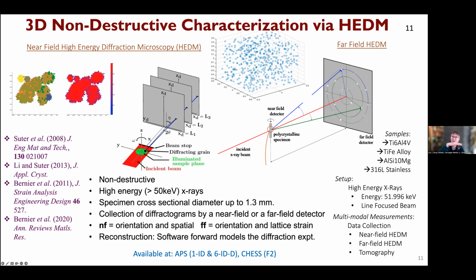And then to get your 3D structure, you repeat. There is a variant of it that we call far field, in which you don't get very much spatial information, but what you do get is elastic strain information. And that complements very nicely what the near field will do for you. So the typical spatial resolution is 1 to 2 microns. The orientation resolution is very good, 1/10 of a degree or better at times. And it's not just APS, you can do this other places, CHESS, ESRF, so on and so forth.